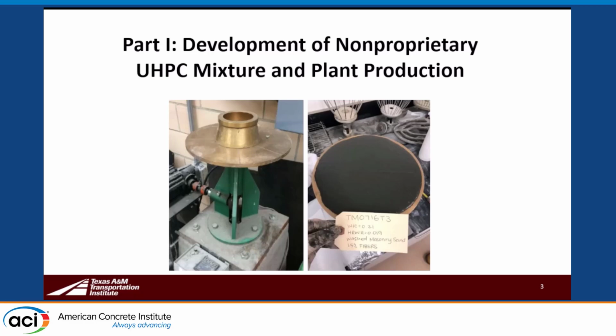And here I just wanted to point out that when looking at the workability of these mixtures, we are doing the slump flow tests, looking at the flow in terms of the diameter of the flow, similar to what you might do for self-consolidating concrete, but using a smaller volume slump cone, if you would like to call it that, that we use here on this brass circular plate. And so we're measuring slump flows on the order of about 9 to 11 inches typically.